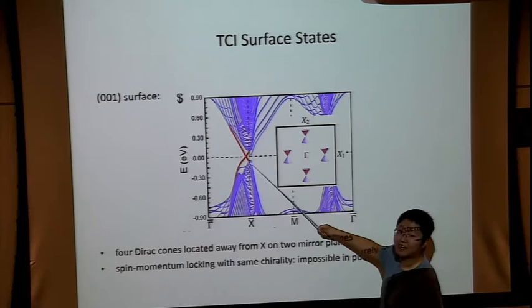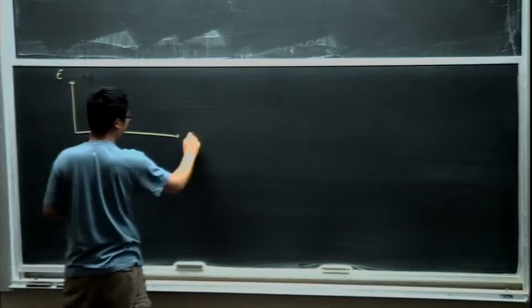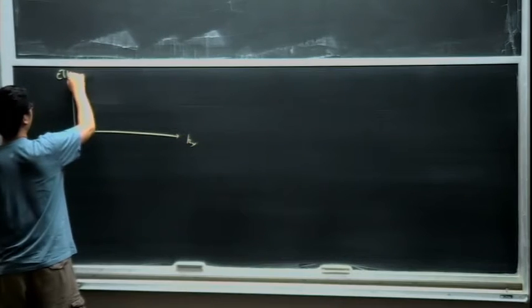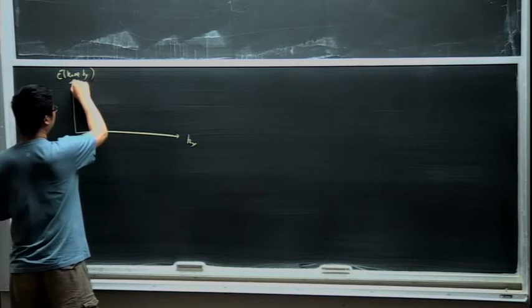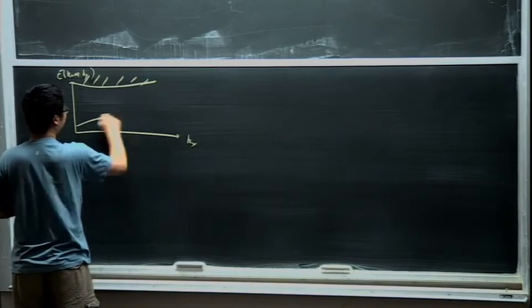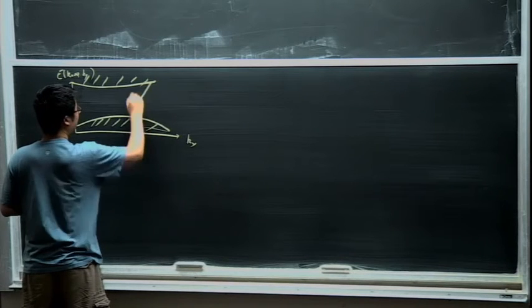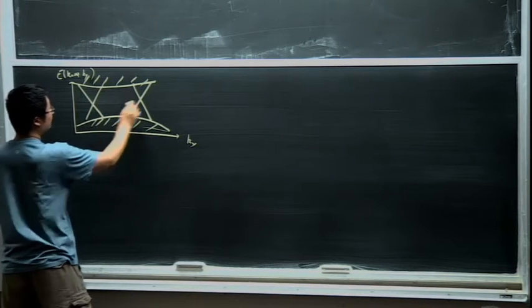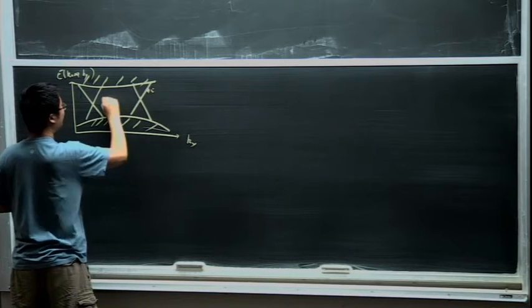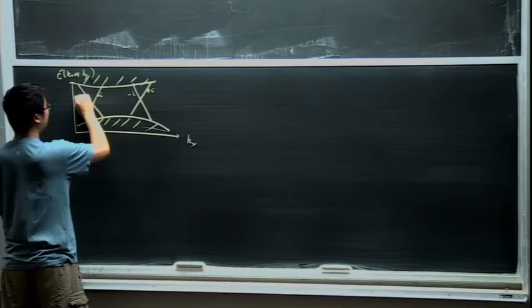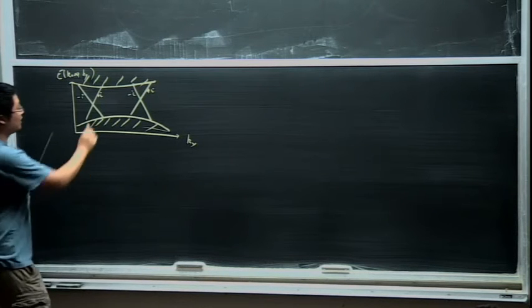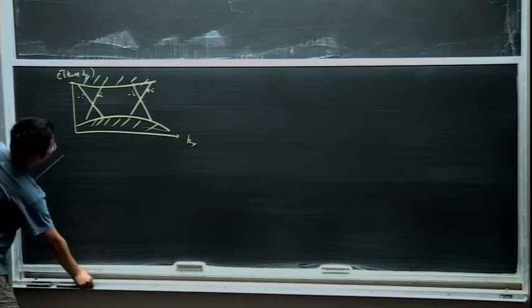The 2 bands that cross each other have opposite mirror eigenvalues, plus I and minus I. And that's why the band crossing is robust. So if I plot the energy as a function of ky on the plane kx equals 0, what we will find is that there are bulk states, but inside the band gap, there are two modes moving to the right with mirror eigenvalue plus I, and two modes moving to the left with mirror eigenvalue minus I. So that's why the crossing is protected by mirror symmetry.